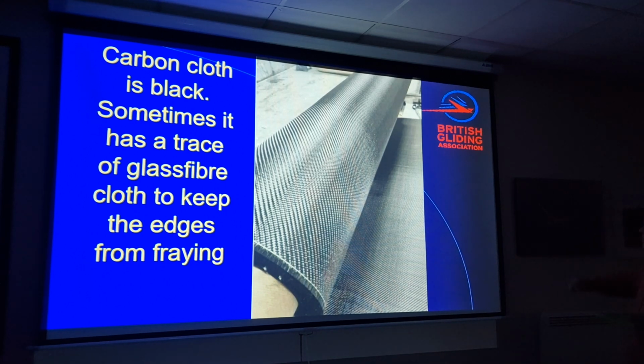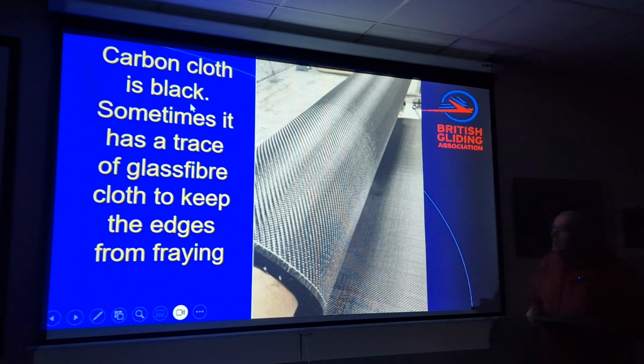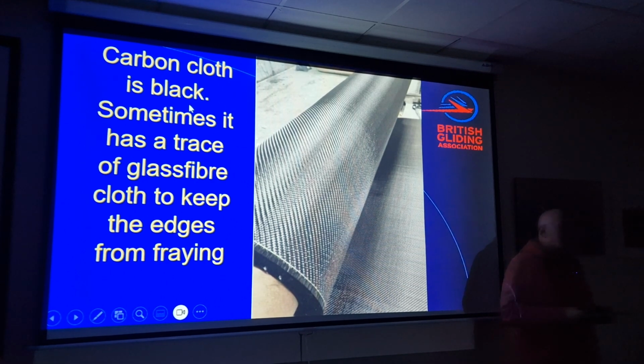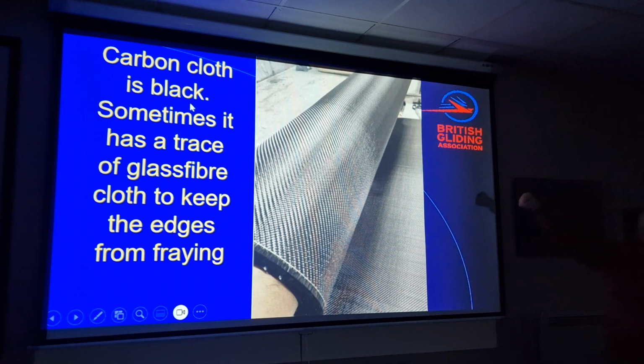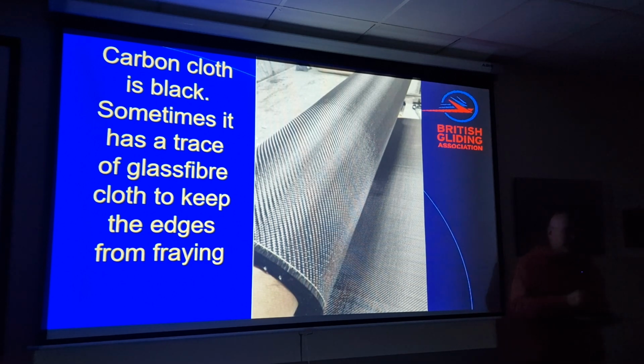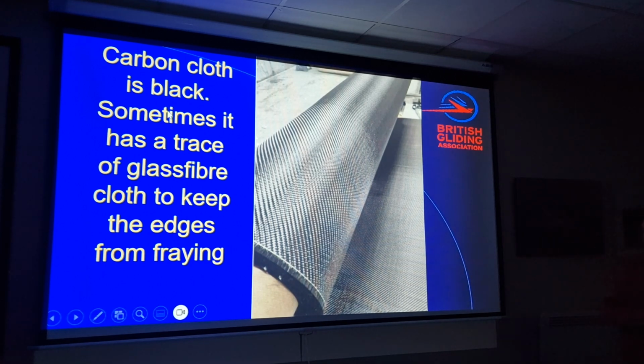About 35 years ago, there was a Slingsby agent, before Pete Wells got it. I think one of the reasons he lost the agency is when you ordered a couple of square metres of carbon fibre, it arrived in an A4 envelope. You took it out, and about 10 pieces fell out. But again, carbon fibre is a very easy material to work. It really is, as long as you obey a few rules.